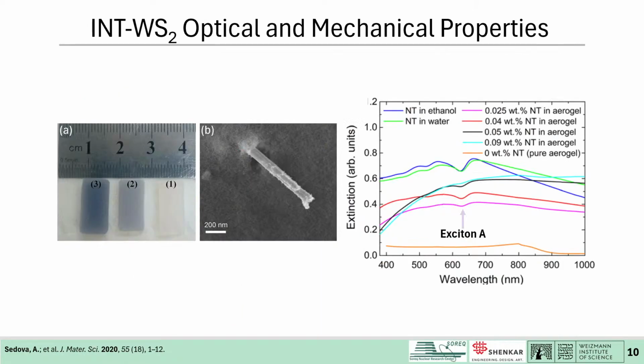Also, we analyzed the optical properties in this matrix of silica aerogel. When we do spectroscopic measurements, usually we do it in solution where particles can constantly rotate. And here we could fix the particles in a constant position. And what we saw is that as we increase the concentration of the nanotubes, the excitonic positions wash out. We basically cannot distinguish them anymore due to the multiple scattering effects.